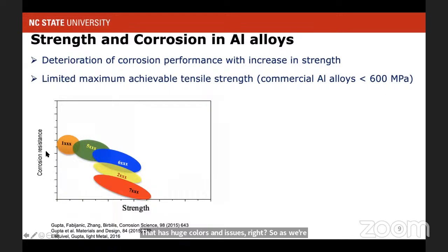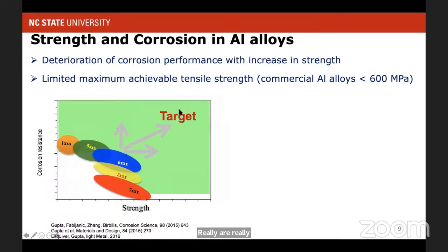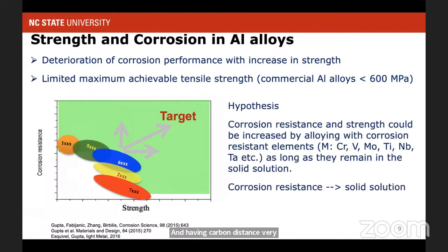So as we increase the strength, we decrease the corrosion resistance. So if I plot corrosion resistance as a function of strength, and it's a very qualitative map, what we'll see is that as you go from 1000 series to 7000 series alloys, you're increasing the strength, but your corrosion resistance decreases a lot, right? Now, what would happen if you can make alloys which have really high corrosion resistance, and also have very high yield strength? So the target being a yield strength of more than a gigapascal, and corrosion resistance very similar to what stainless steels have. And so we put some of our hypotheses together, making a kind of solid solution, and I'll go over it and see what we get, right?